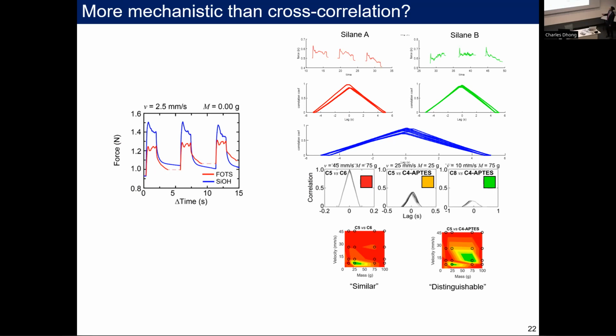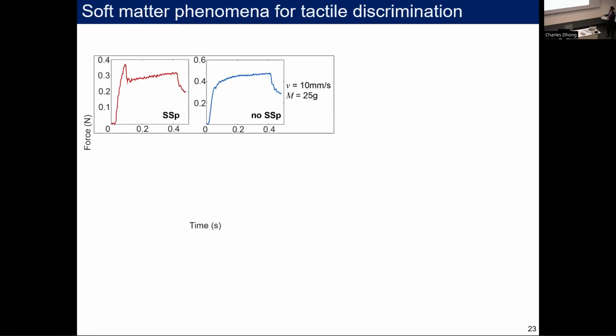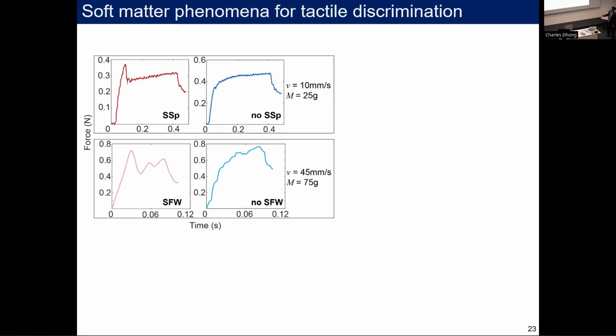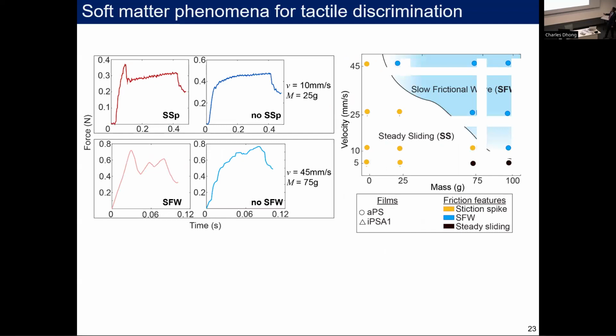How can we maybe connect some of these wiggles, right, to something a little bit more into what people actually do? So the origin of these wiggles, right, are mechanical instabilities between sliding, elasticity, and adhesion. So one of the things we started to look at is, well, maybe can we create a phase diagram based on this? So here's a stiction spike, and here's no stiction spike. These we call a slow frictional wave, and this is the lack of a slow frictional wave. So we just tried to find whether these instabilities occur or not. So doing that, we can take our material and categorize them by where these instabilities occur.